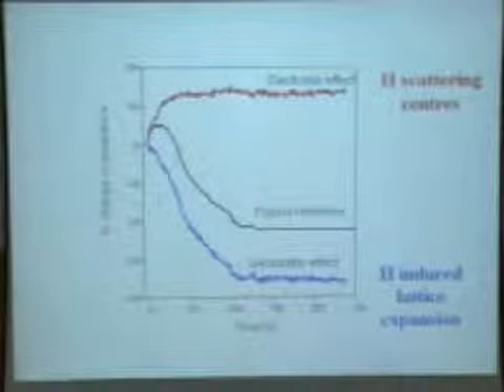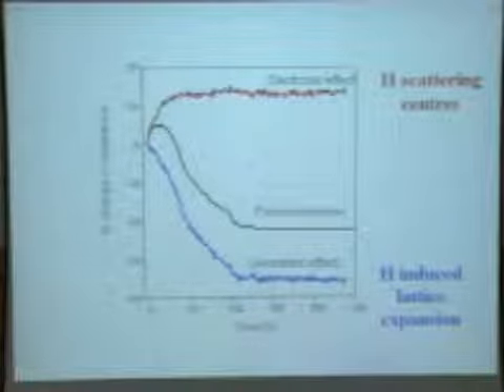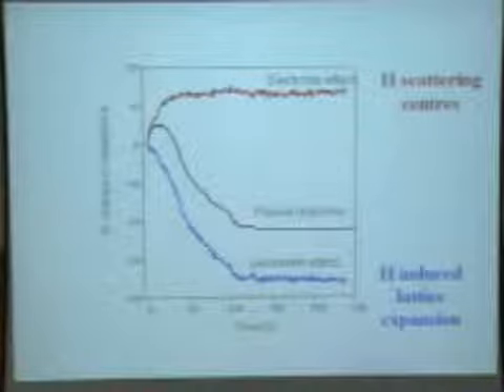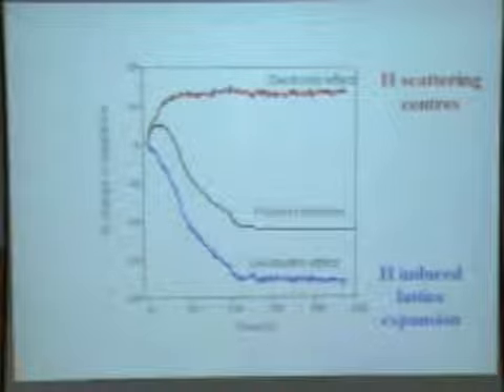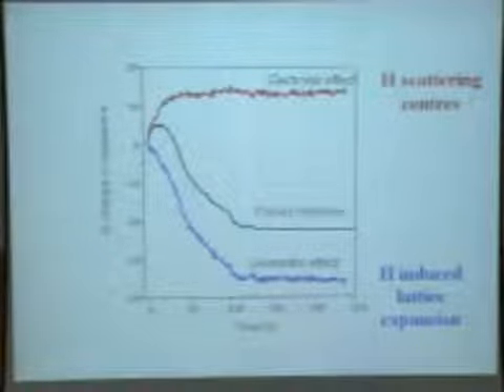What is happening is that there are in fact 2 important effects. This pulse response is actually a superposition of 2 effects. One is the electronic effect. The electronic effect is hydrogen acting like scattering centers in palladium. They scatter electrons and increase the resistance. So the resistance increases. When the slow saturation response is there, that means this effect is dominating.